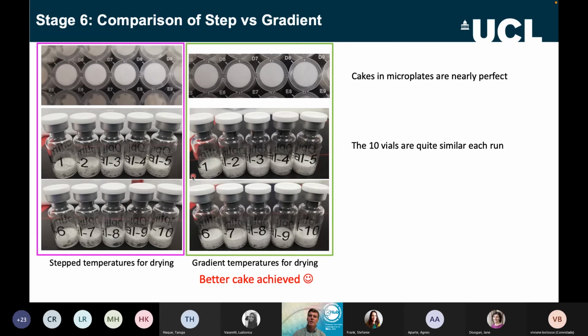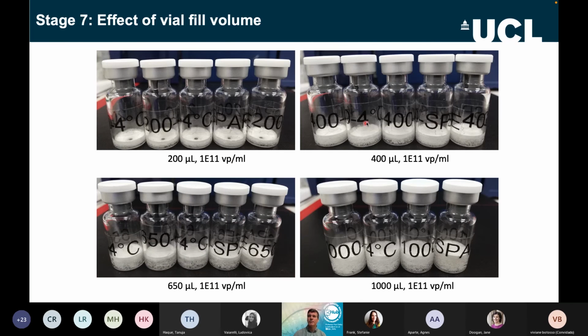So we then thought, maybe we can adjust the fill volume and see how important that is for performance, because that's the main difference. So we looked at fill volume. We went from 200 microliters up to a mil fill, and these are the cakes that come out. We can see 650 is the worst, and 1 mil seemed okay. So something to do to understand why that happened, in terms of appearance.